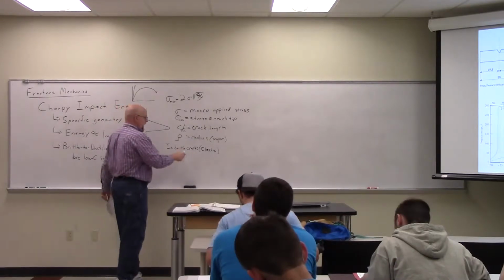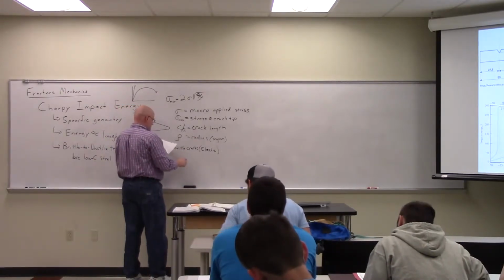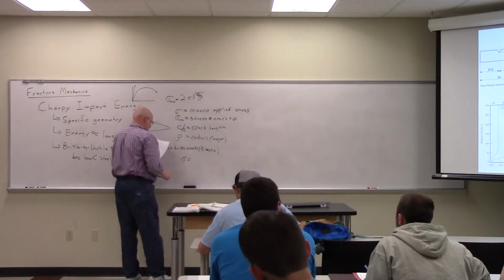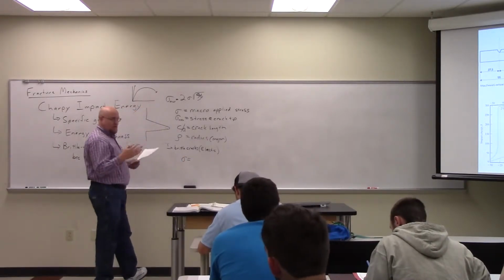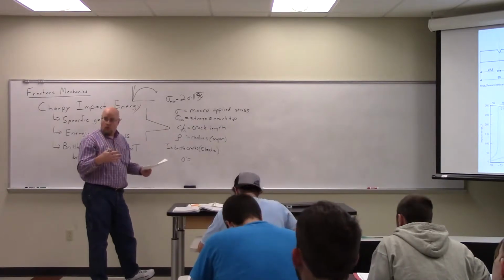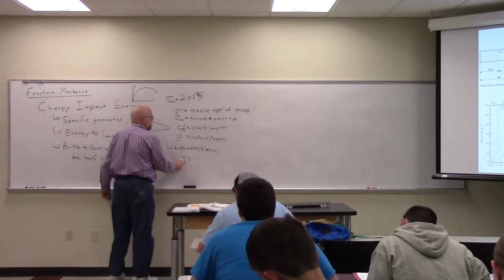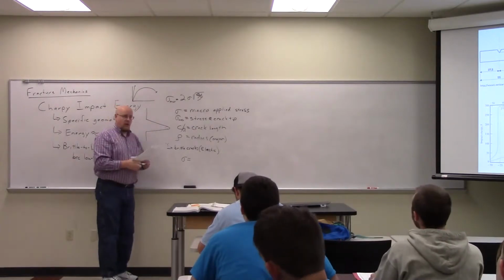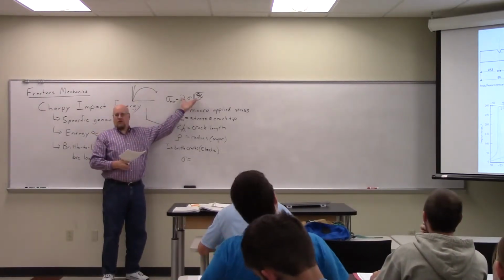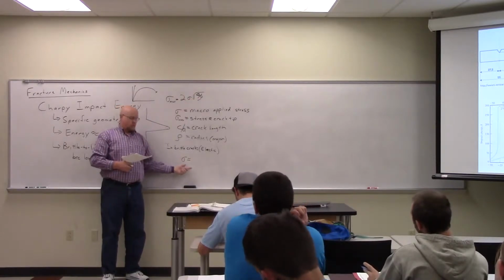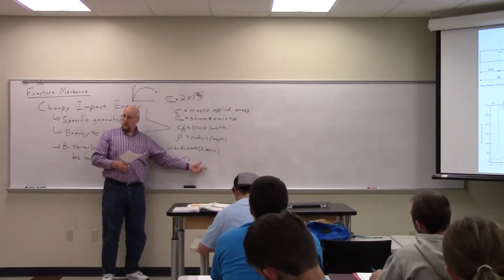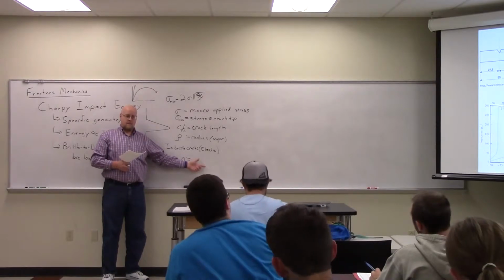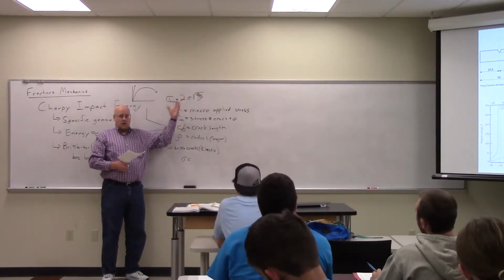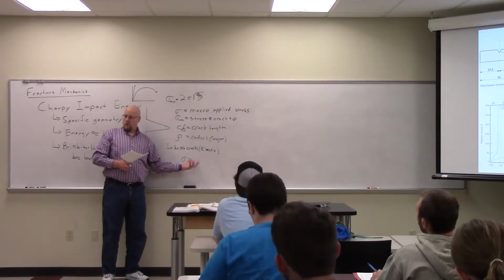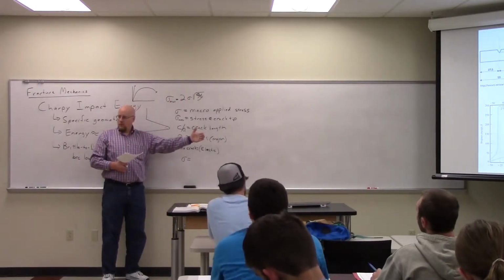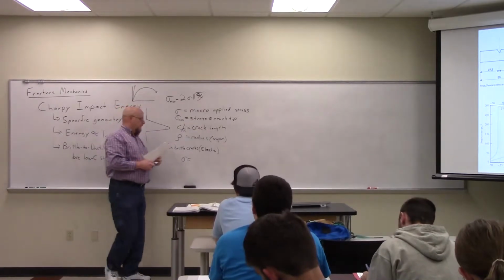So in a brittle crack, where you're cracking the thing in an elastic regime, the stress needed to make that crack grow, this stress, would be essentially the max stress when the crack starts to grow. This one is the stress caused by the external applied load. This is going to be the stress needed to make the crack grow. Understand the distinction? This is the applied, and this is the critical. So when the applied equals the critical, the crack grows. Does that make sense? Okay.